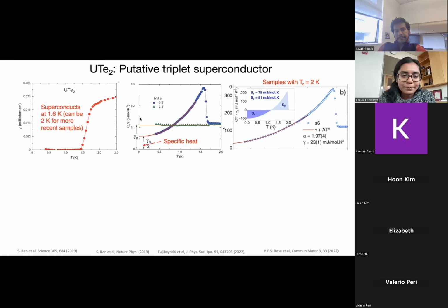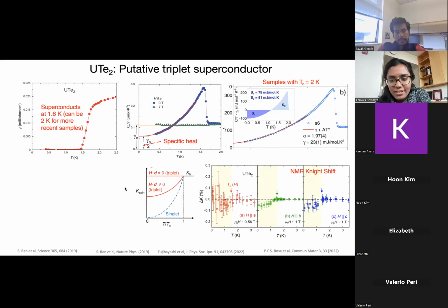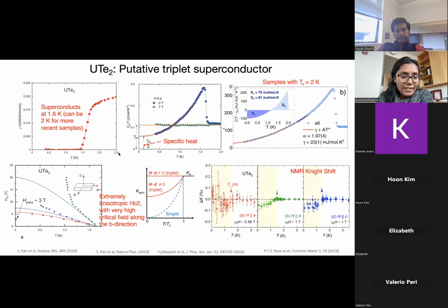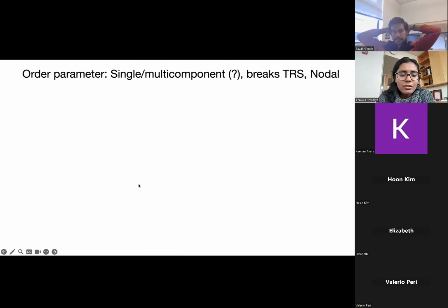The more convincing argument for spin triplet superconductivity comes from Knight shift measurements, where people saw that the Knight shift does not drop by a lot. It drops barely by 0.05% across TC, and this has been verified by multiple groups in the world across multiple samples. Similarly, the magnetic field HC2 measurements are extremely anisotropic in all three directions. In the B direction, the critical field is pretty large. It can probably go around 40 Tesla, which shows some unconventional pairing mechanism already.